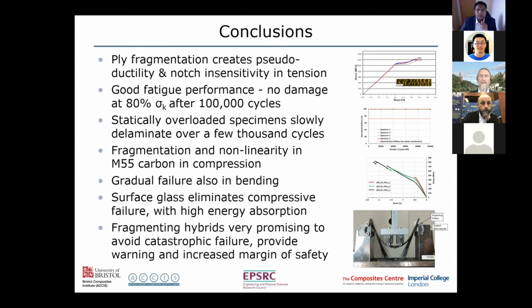There's been quite a bit of work we have published on that, which I haven't touched on today. But we also need to keep the plies thin. If you hybridize at fiber level, then you get some benefit at that level. But in this case, we're getting the delamination occurring and the fragmentation at ply level, which has some advantages in creating some additional pseudo-ductile strain. So I think both approaches can be done, but it's quite difficult to actually achieve full fiber hybrids. There are also alternatives. You can do it at tow level, but we think that doing it at the ply level is probably the best and most flexible way. And it's also relatively easy. You can make prepregs. You can combine these thin plies together to make a pseudo-ductile prepreg by putting the different fibers together, creating a material which can be used very much like current prepregs.